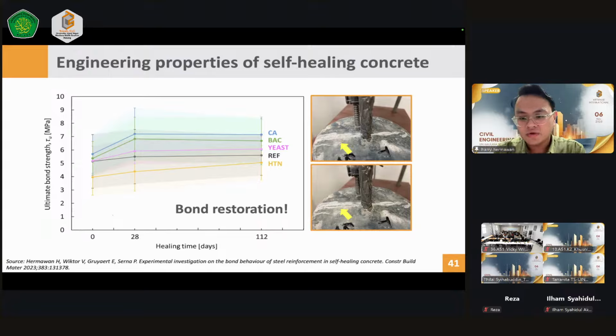So from the picture that I showed also here, I also showcase that even after healing, when I do the pull-out test, the crack will reopen again. If you see the picture on the bottom, you see there was a crack line being reopened even after healing. It also shows that the healing products inside there are not as strong as the concrete itself.